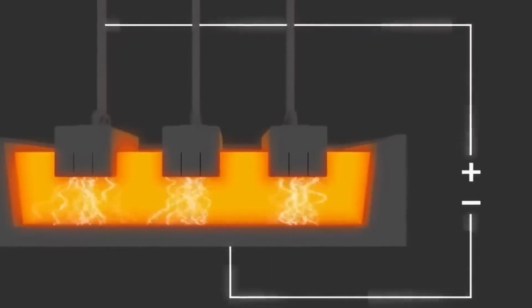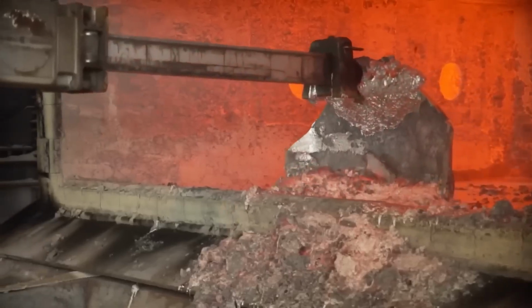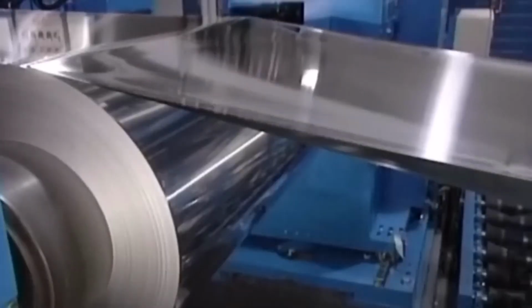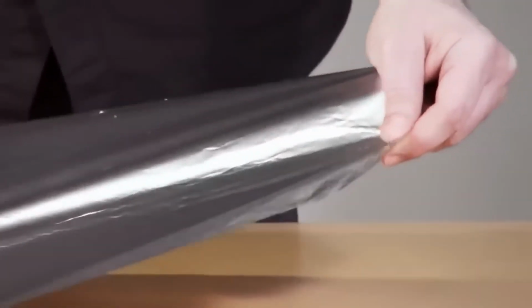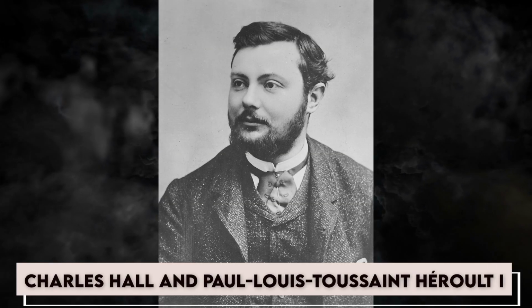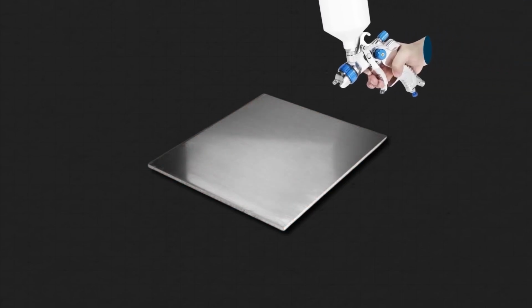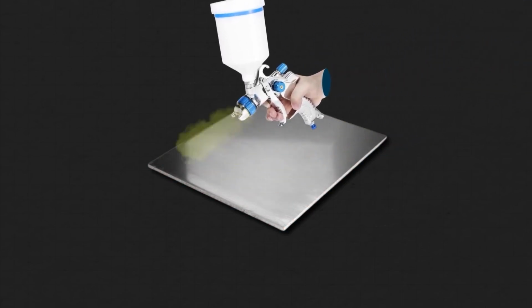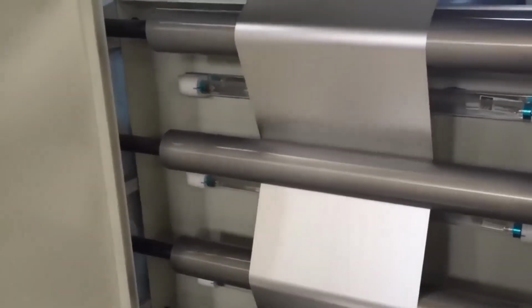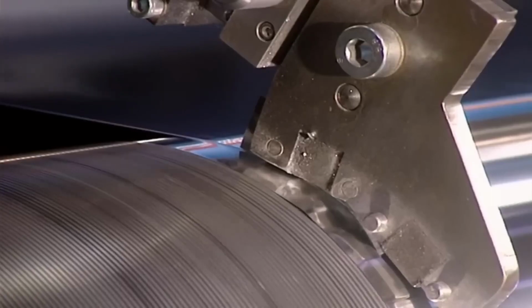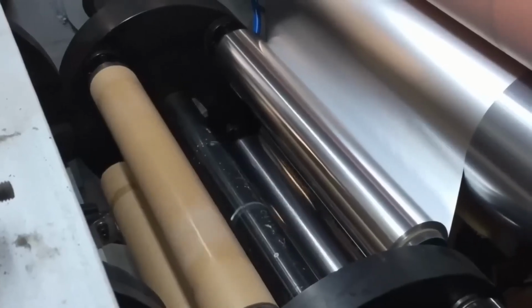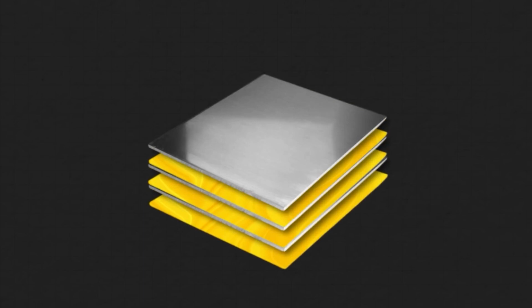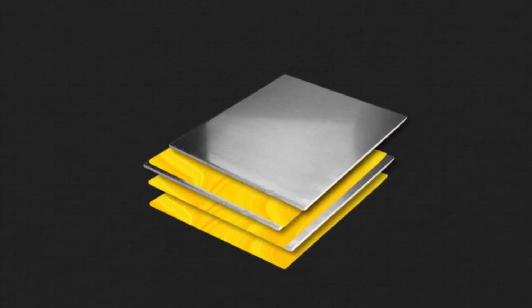Smelting separates the aluminum-oxygen compound produced by the Bayer process, and the next step is extracting pure metallic aluminum from bauxite. The procedure currently used derived from the electrolytic method invented by Charles Hall and Paul-Louis Toussaint Héroult. First, the alumina is dissolved in a smelting cell, a deep steel mold lined with carbon and filled with a heated liquid conductor that consists mainly of the aluminum compound cryolite. An electric current is run through the cryolite, causing a crust to form over the top of the alumina melt. When additional alumina is periodically stirred into the mixture, this crust is broken and stirred in as well.